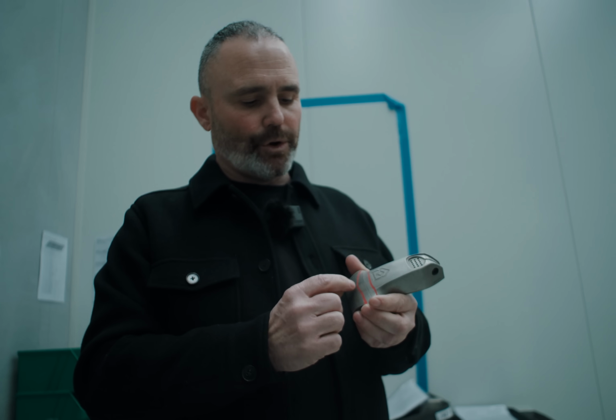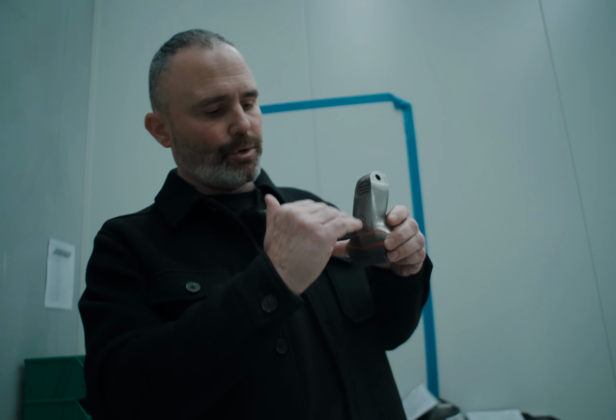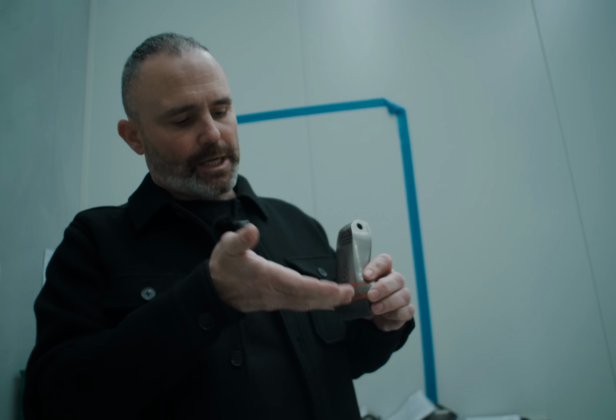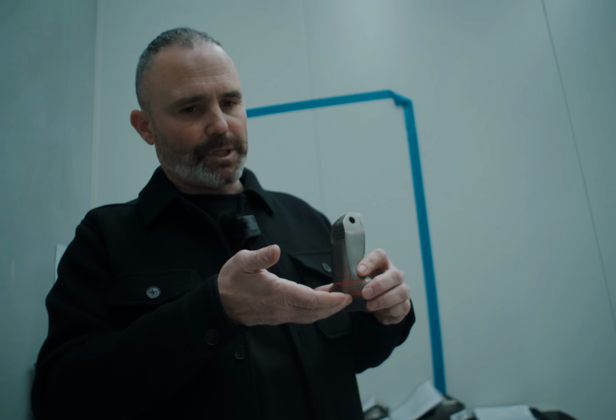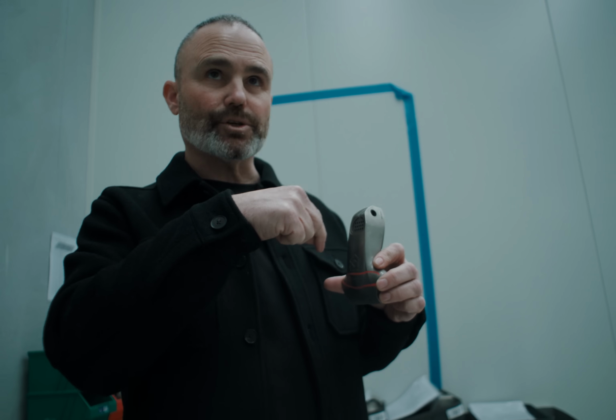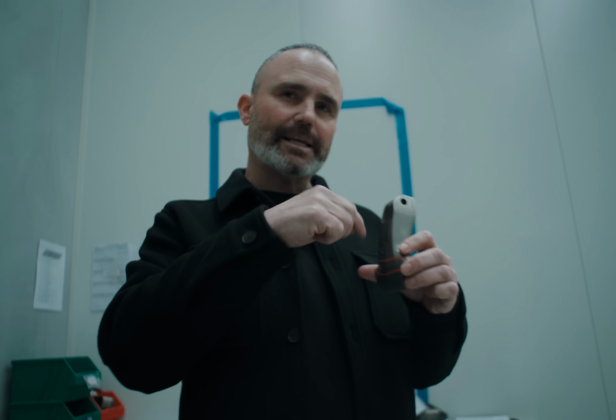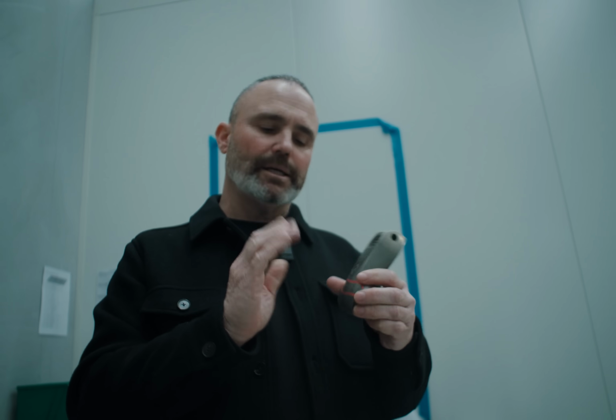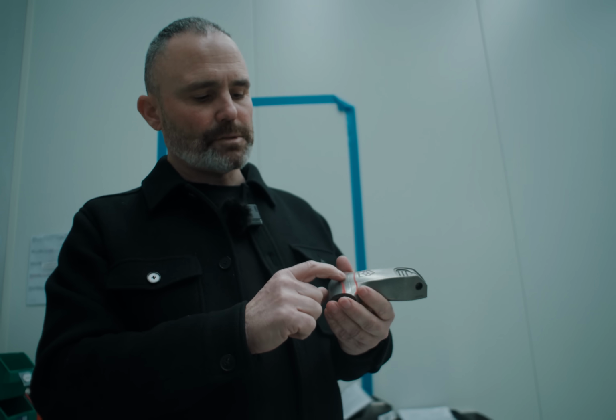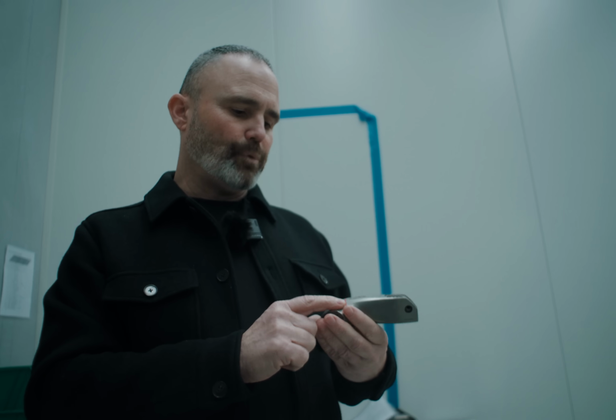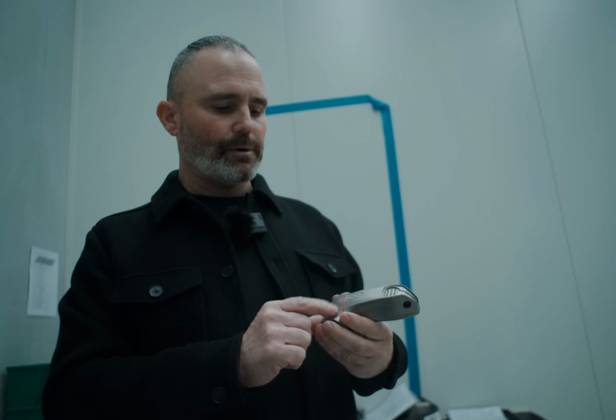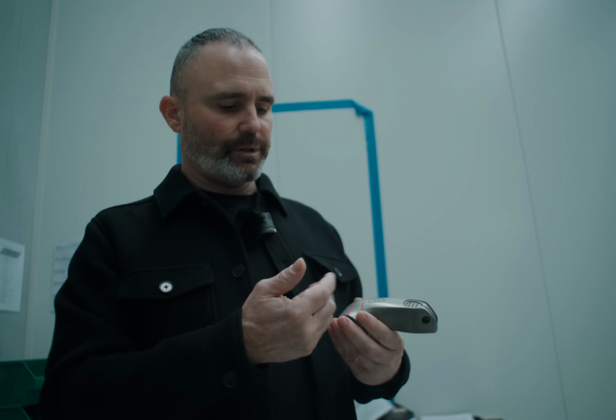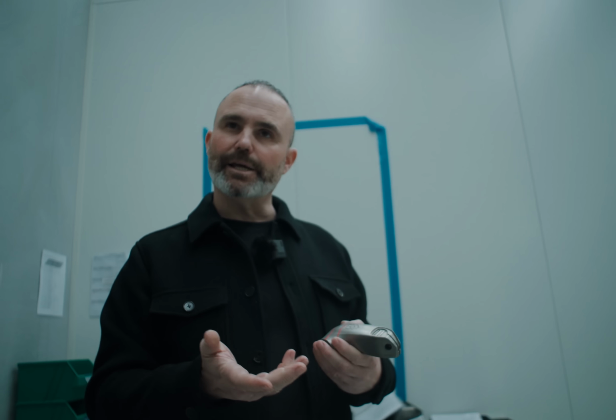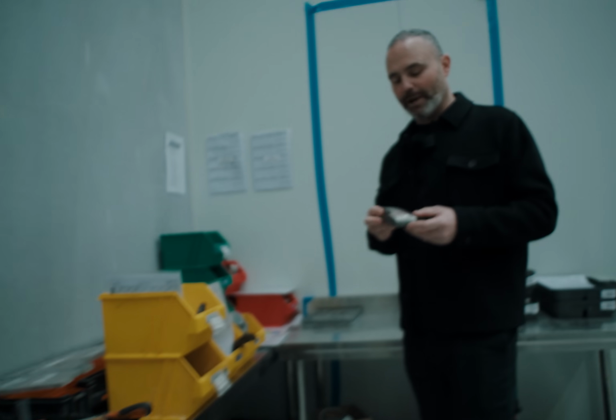And if it lets go, the part below, like let's say it's building it up this way, the part below shifts a little bit compared to where the laser thinks it should be. And so then the next layer is just that little bit over, and it's, you know, it's microns, but you can see it. And if we were to try and remove that with grinding or polishing, we'd thin the metal out too much and it'd be dangerous. So we just throw that away. Well, not throw it away, we recycle it.